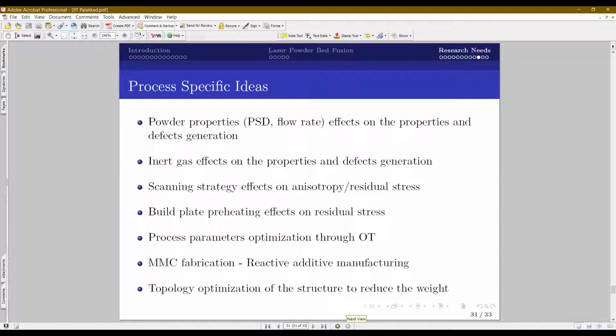So I urge people to study powder property effects on the final component properties and defects. And similarly, inert gas. Presently, we find most of the components are printed under an ambience of argon. How about nitrogen, which is less expensive? I expect similar efficacy with nitrogen. So how about its impact on the properties and defects? There are some studies that say nitrogen is much better than argon in steels. But still there is no clarity. It may be the case that nitrogen may be more suitable for some grades and argon for some other grades. So we need to understand these inert gas effects on the properties and defects.